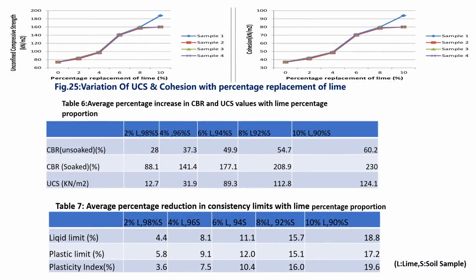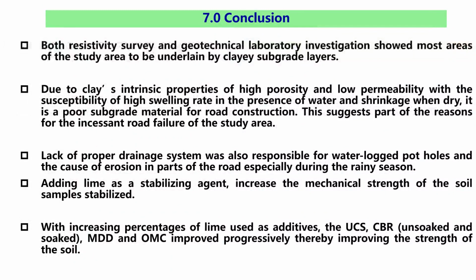So the effect of the stabilizing agent on subgrade strength was observed, and generally it has led to significant improvement in subgrade soil strength. From the table, we can see that the effect of lime on the California bearing ratio test, both soaked and unsoaked, increased. Maximum dry density reduced, optimum moisture content increased, unconfined compressive strength generally increased, the cohesion also generally increased, while the plasticity reduced. So in general terms, the effect of lime on the strength of the subgrade soil was found to significantly improve the strength of the soil using lime as stabilizer.